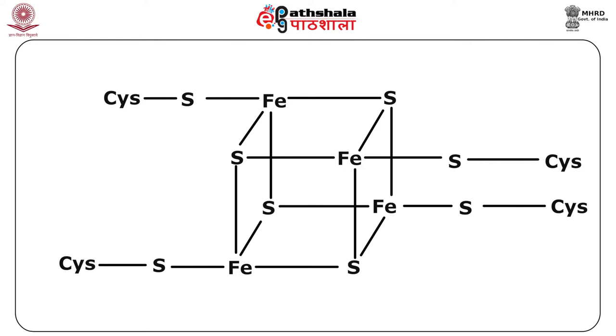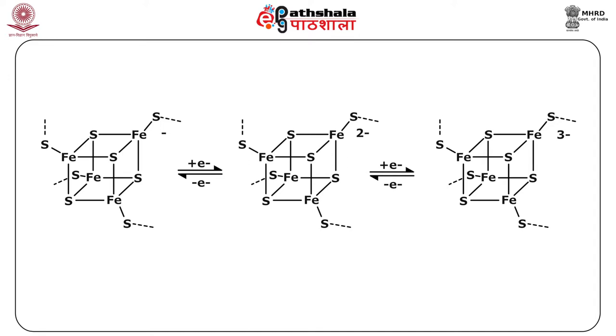The figure depicts 4 iron ferredoxin. Now these Fe4S4 electron transfer proteins may be further subdivided into low potential bacterial type and high potential HiPIP ferredoxins. Low and high potential ferredoxins are related by the redox scheme given in the figures. In HiPIP, the cluster shuttles between 2Fe3+, 2Fe2+, and 3Fe3+, 1Fe2+. The potential for this redox couple comes in the range of 0.4 to 0.1 volt. Two pairs of oxidation states, 3Fe2+, 1Fe3+, and 2Fe3+, 2Fe2+, are found in the bacterial ferredoxins with a potential in the range of minus 0.3 to minus 0.7 volts.